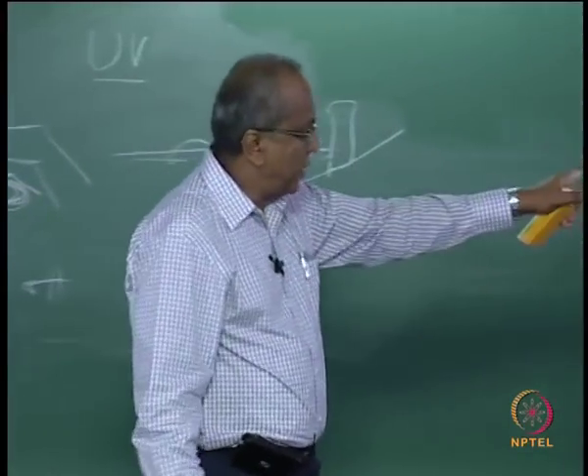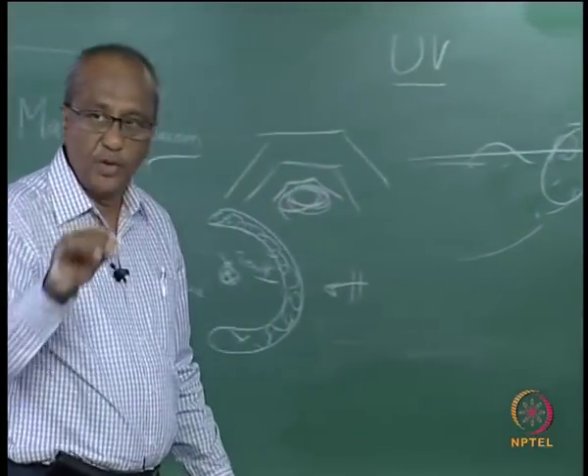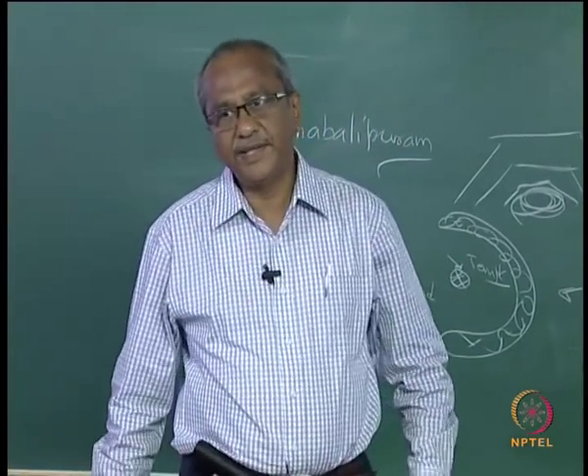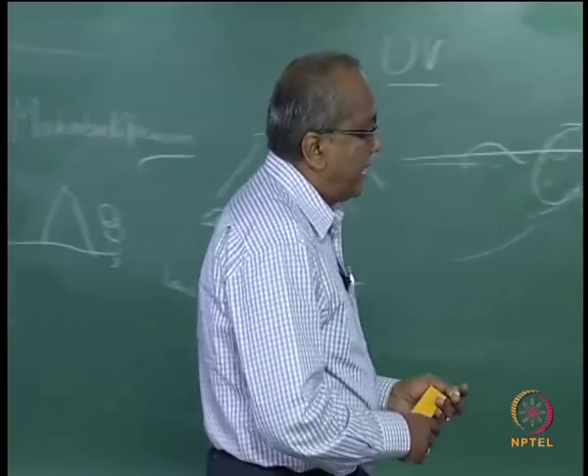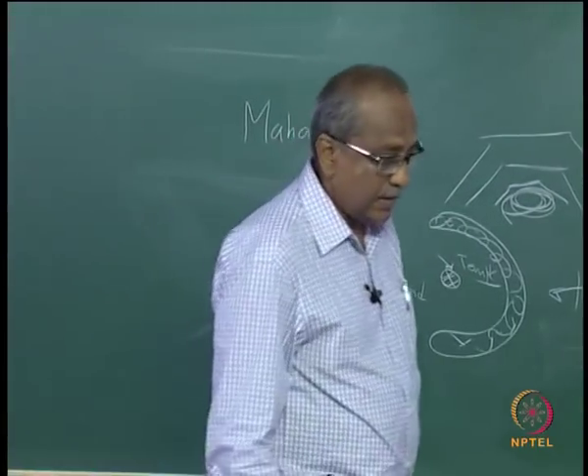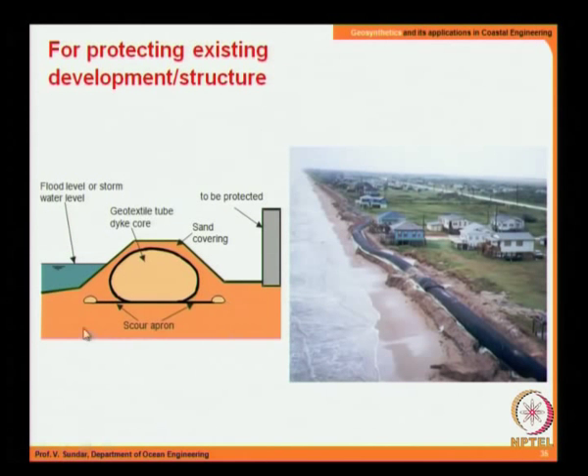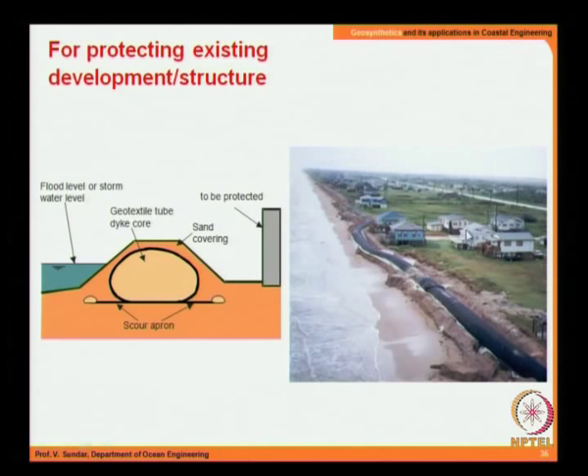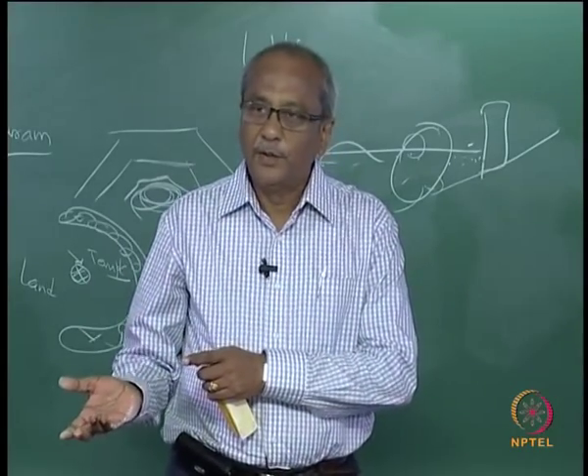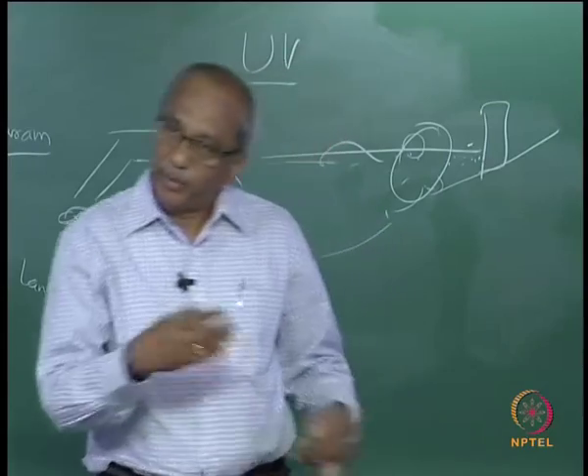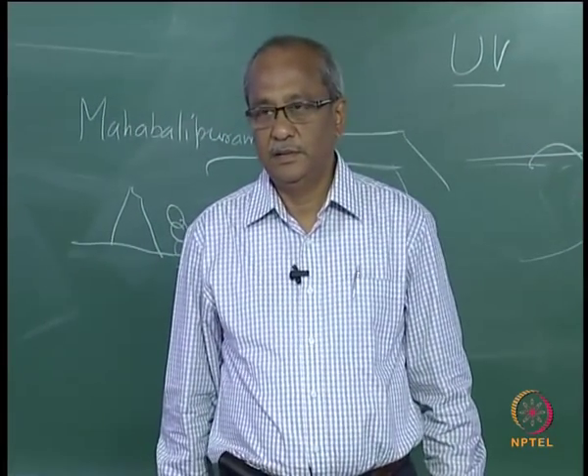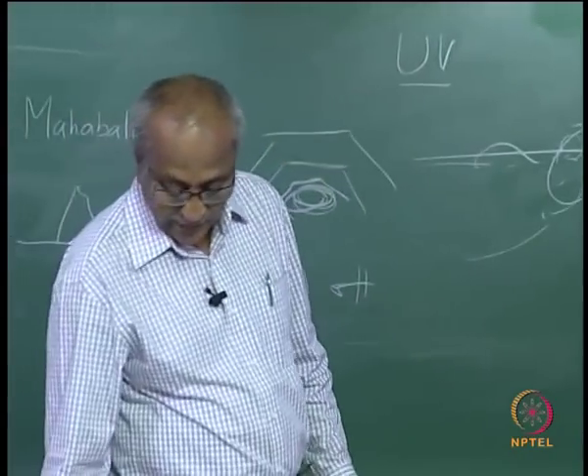UV ultraviolet radiation is one of the biggest problems in dealing with geosynthetic materials in tropical countries. If the geotube is totally submerged there is much less problem, but if exposed it will have UV problems. When sand is used to cover the geotube, that sand itself can erode — you must be very careful in finalizing the design, because by trying to protect one structure you could build another that ultimately both are lost.